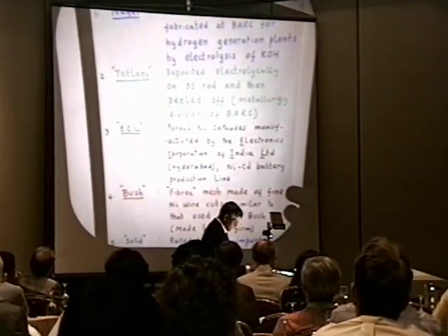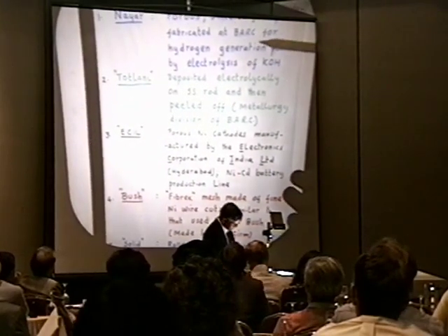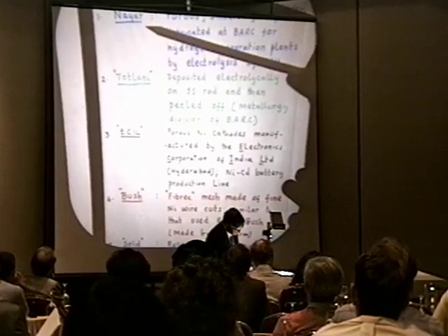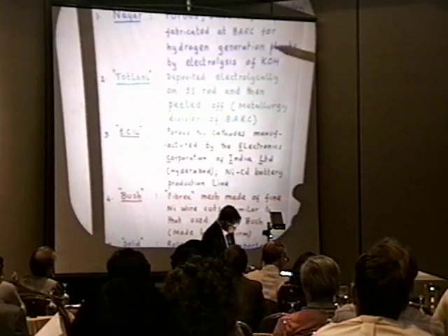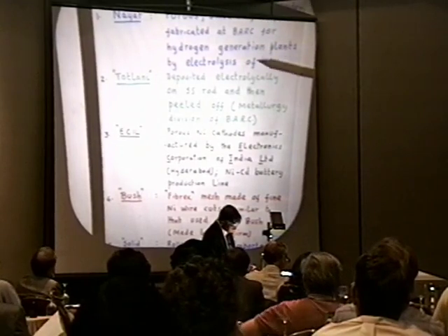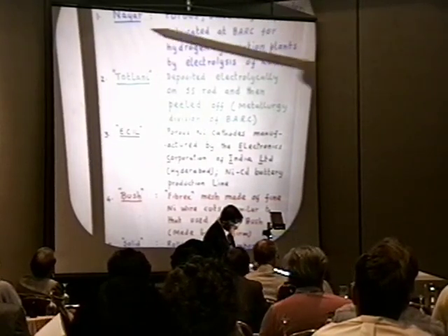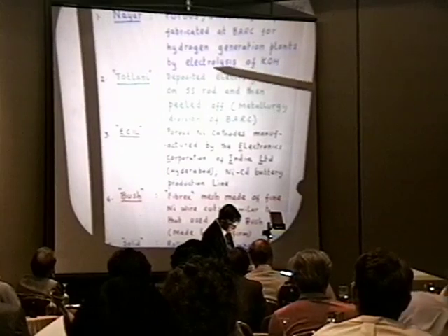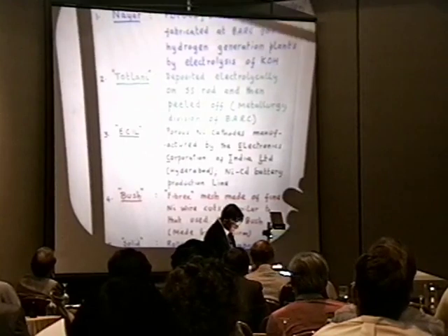Most of the experiments were conducted with nickel, and we have used 5 types of nickel, which are named as follows. I will very briefly describe it. The stuff known as Nayar nickel is a porous, sintered form. It is sintered from the powder, nickel powder. It is fabricated at BARC by this gentleman. He has been making hydrogen generating plants by the electrolysis of KOH. So these were readily available when we got into this.